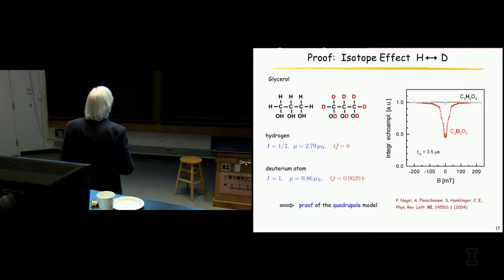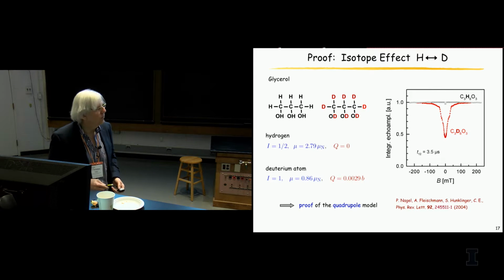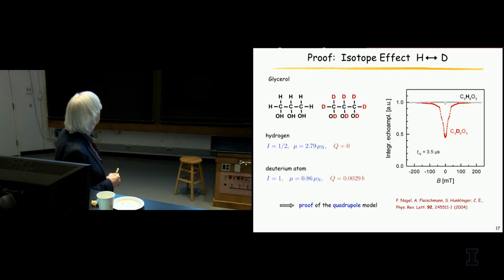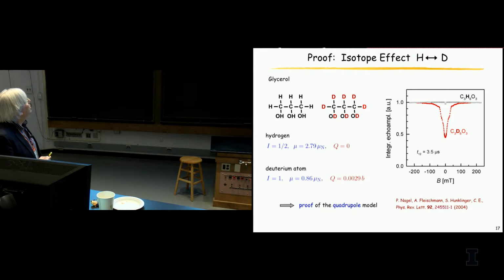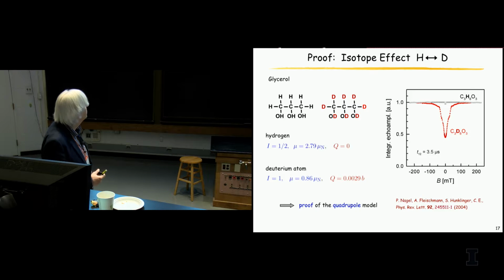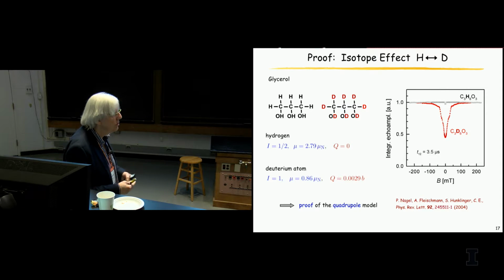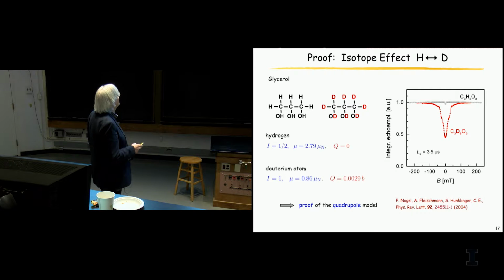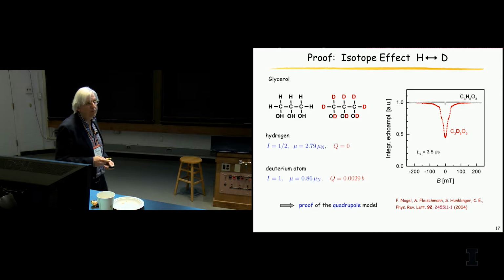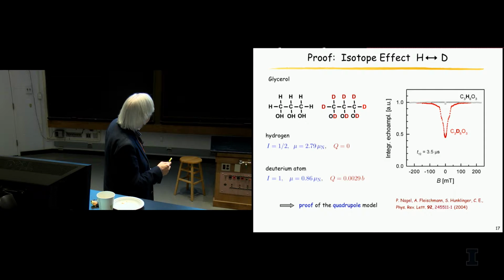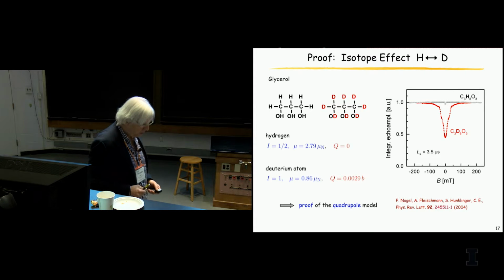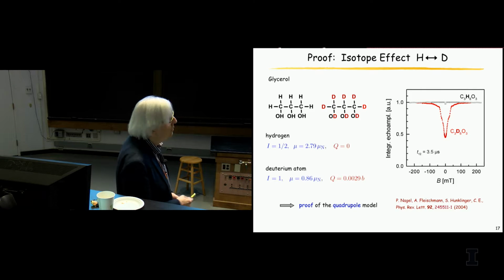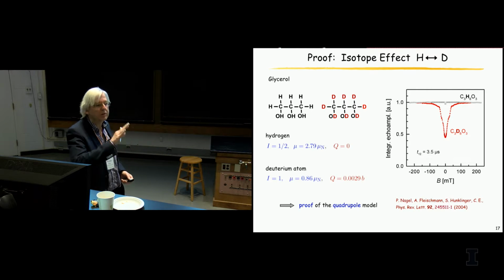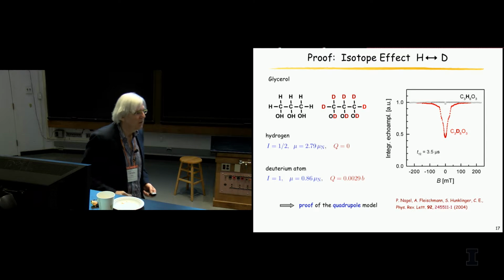Now, we tested that a little more rigorous in the following way. We use glycerol. Normal glycerol has only atoms with nuclei with spin 1/2 and no quadrupole moment, and you can deuterate that. You have the same kind of glass. If you cool glycerol down, it forms a glass. And then we repeated this measurement of the microwave echoes. So for the deuterated stuff, we saw a strong magnetic field dependence, and for the normal glycerol, there was basically nothing. A little bit of that, which we assigned to dirt, which it wasn't, but this is not the topic I want to discuss here at the moment.